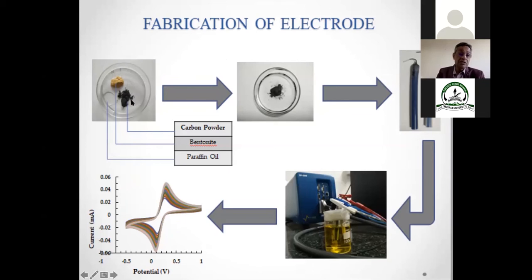Here is the material. You can see the carbon powder and the organically modified bentonite. Along with the paraffin oil, we have prepared the paste. Nowadays we are not using this paste-based method. Now we use a glassy carbon electrode, or a screen-printed electrode, or a disc with some kind of polymeric material. These are the newer technologies that we are trying to introduce here.